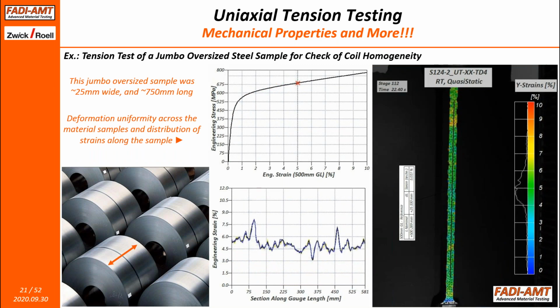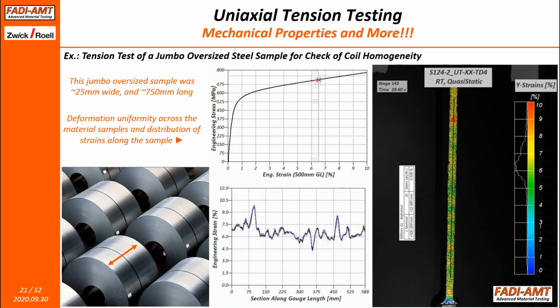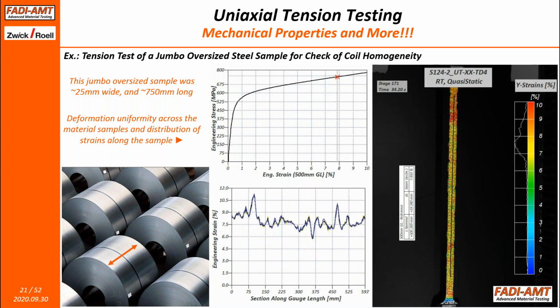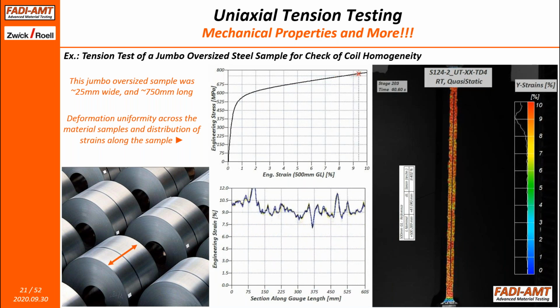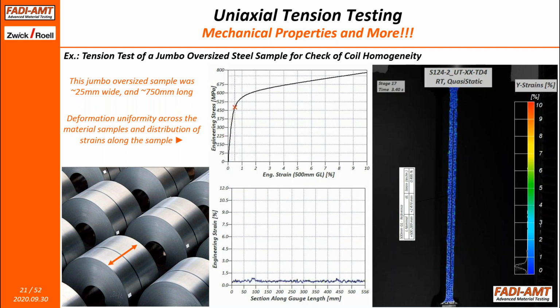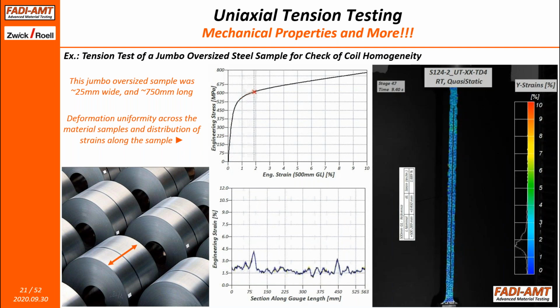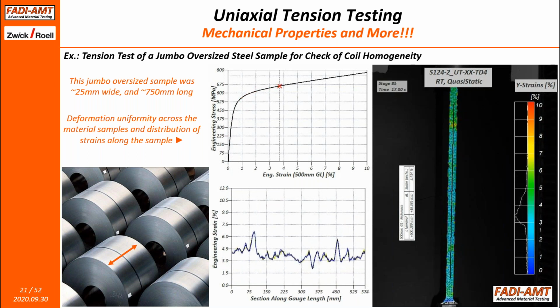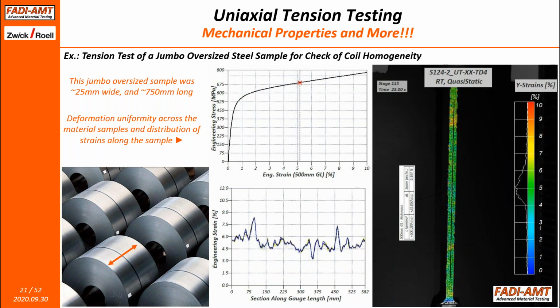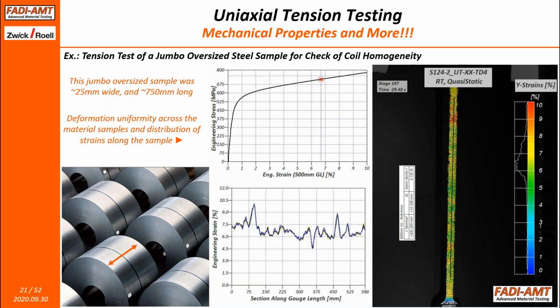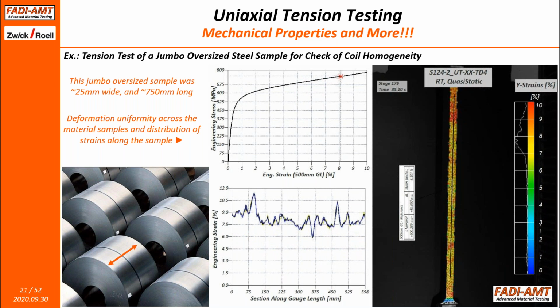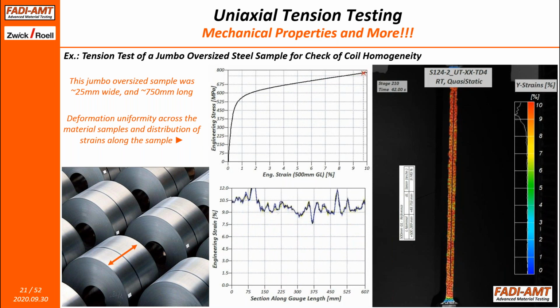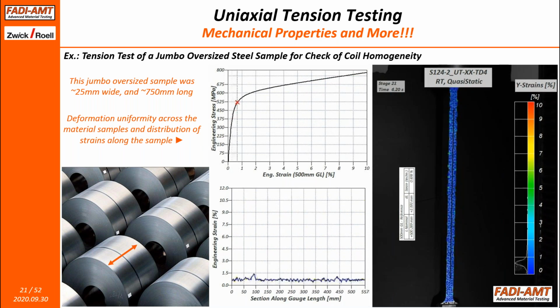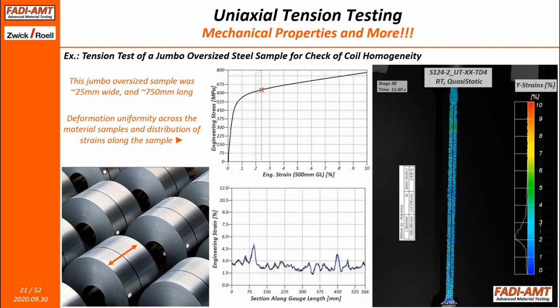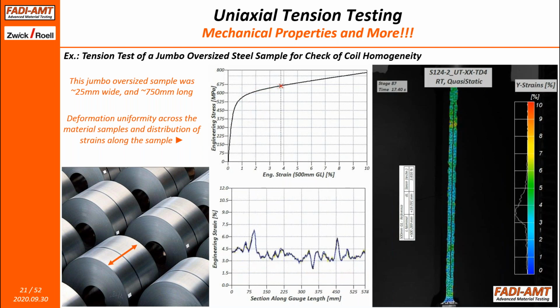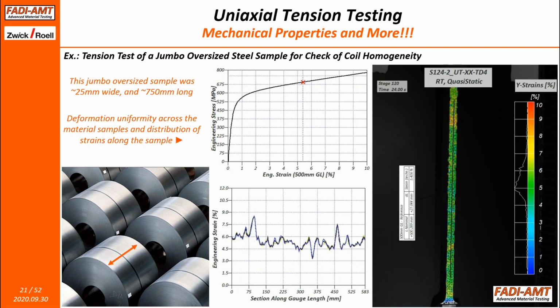And you can see this very clearly in the bottom left corner of this video. You can see how the strains are not uniform at all in this particular coil, and it was a development coil, and that was the intention of a test like this, which is to show whether the coil is homogeneous or not. And that can be done with the DIC, cannot be done with conventional extensometry, because not only do we want to cover a very large area, but also we want to cover the entire spectrum of strains along the entire sample, and that is the section view that you can see there.